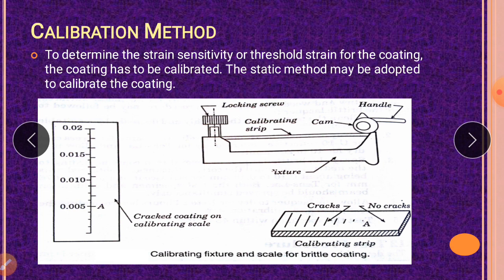So we make this calibrating strip and apply some load over it, and we can see the scale. This crack coating on the scale represents at what distance what amount of strain develops. You can see the cracks. The strip, after loading, experiences the load at its free end and is fixed at one end, so the crack patterns are generated like this: higher wherever the stress is more and lower wherever the stress is less. You can see the crack pattern formation.